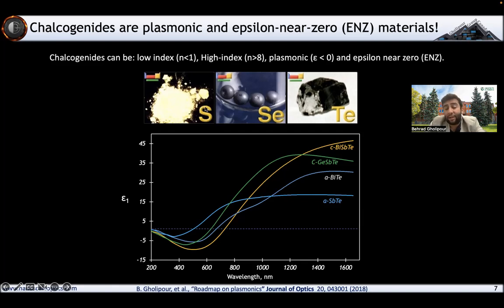In particular, the alloy systems that we are very interested in, because of the applications that I explained before, are the chalcogenide family of materials. Chalcogenides are usually alloys of metallic elements, usually with sulfur, selenium, and tellurium. They can have low refractive indices. They can have high indices, more than n equals 8, which is very unprecedented. They can have plasmonic properties, as I showed you, or epsilon near 0 properties, which is, again, an area of very intense activity these days in the world of nanophotonics. So they have very similar dispersion.